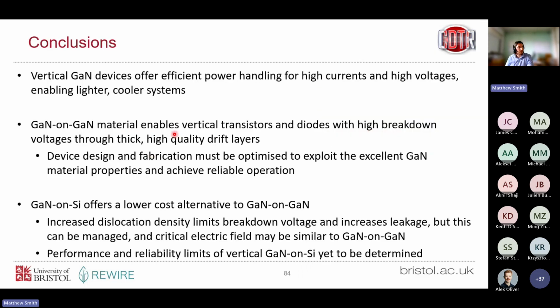Great, and that brings me to my conclusion. So hope I've shown that vertical devices can offer very efficient power handling for high currents, high voltages, for cooler, lighter systems, some really important emerging applications where they should really make some commercial headway. We've shown GaN on GaN devices, this first, second, and third generation, where we can improve performance, so maintain our on and off state properties, and also achieve high reliability through optimization of our device design and fabrication. And then a little snippet into potentially the low cost future for vertical GaN, where we can look at non-native substrates. So controlling the dislocation density in GaN on silicon and moving towards high breakdown voltage GaN on silicon vertical devices.